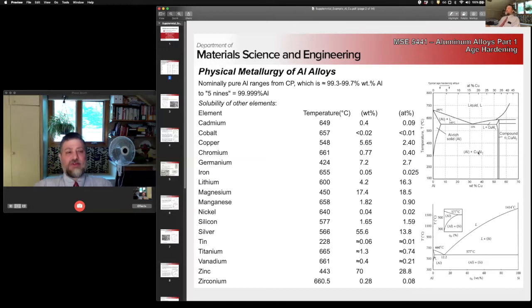They don't have too much of an ionic character, but they're very hard to cut, and they form secondary phases. So that's the strategy for developing aluminum alloys for the most part: trying to find things that will give us a nice fine dispersion of secondary phase particles so that we get a lot of strength, but that we don't end up being too brittle.